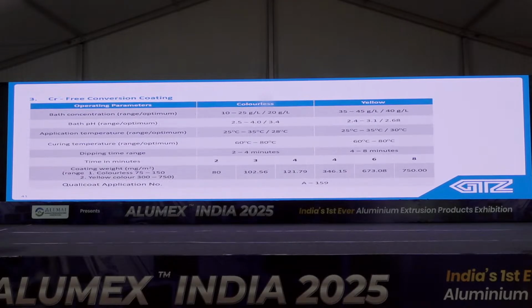Chromium-free colorless has a little lower consumption than the yellow color. Yellow color is just double of colorless, because the thickness of this coating is also higher. pH is similar. Application temperature is room temperature. Curing temperature is around 60 to 80 degrees. Dipping time varies. For colorless, as coating weight is less, it is 2 to 4 minutes, and for yellow it is 4 to 8 minutes. The coating range for colorless is 75 to 150 mg per meter square, and for yellow it is a little higher, 300 to 700.